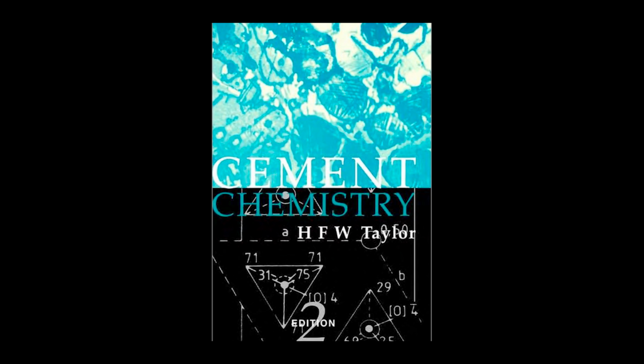Okay. And finally, expansive cements, designed to counteract the volume loss associated with drying. Expansive cements, like Type K, are engineered to dramatically increase ettringite formation. They rely on a phase called C4A3S-bar as a key ingredient, mixed with high amounts of gypsum or anhydrite. The goal is to induce a controlled internal expansion, either through the physical forces exerted by the growing ettringite crystals or the swelling pressure of colloidal ettringite attracting water. This internal expansion compensates for the drying shrinkage that occurs later, minimizing cracking and often leading to self-stressing properties.